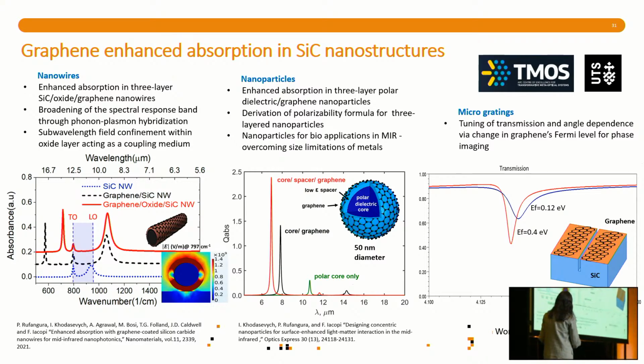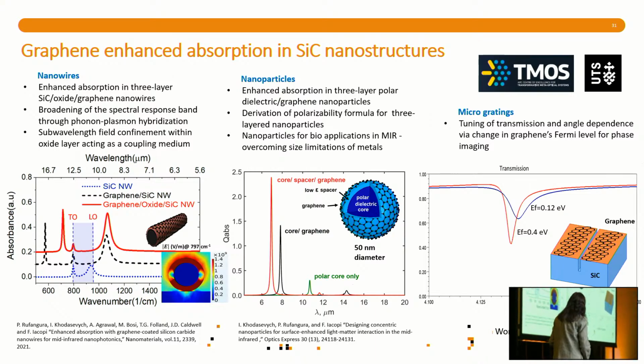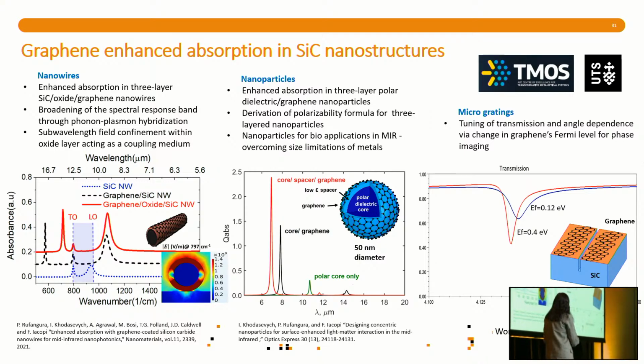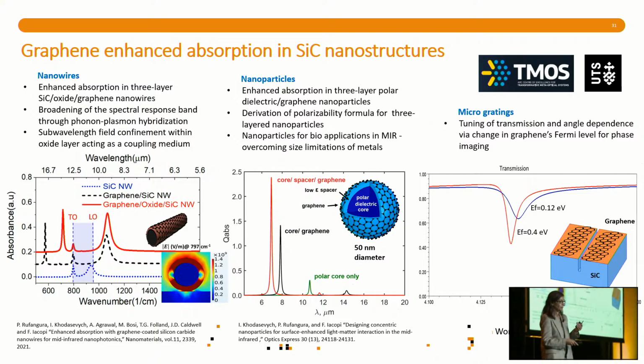Because also notice that when we go from here to there, we lose a lot of the carbon because we are using the carbon to make graphene. So we have less material, not more, but we have much more absorption. And last but not least, we concentrate the field, particularly for M1, into that low refractive index, intermediate layer in between the graphene and the silicon carbide core. So this is extremely interesting in terms of enhancing IR absorption with this system.